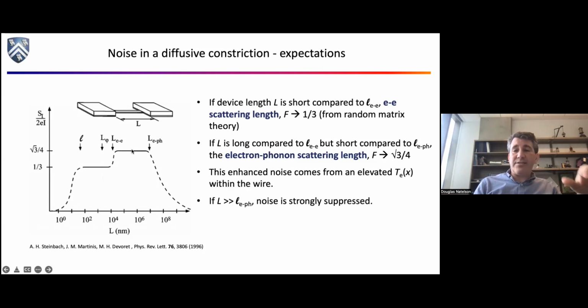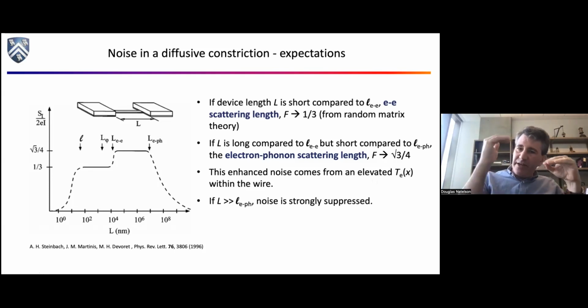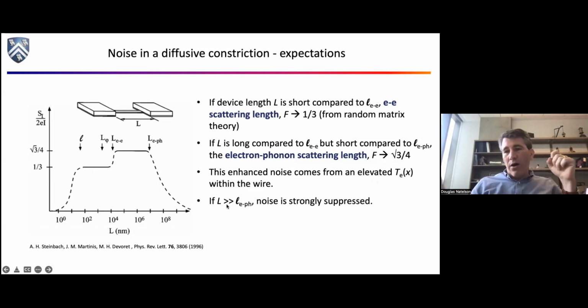Now, if the wire is longer, so the electrons can exchange energy with each other, you can actually work it out that the Fano factor goes up, and it's supposed to be √3/4, which is about 0.433 for those who actually care about the number. And one way to think about that is that there's some effective electron temperature inside the wire where the electrons have shared energy amongst themselves. And that gives you an elevated noise, okay? Now, if the wire is too long, then the electrons can lose their energy to the vibrations of the atoms. And that's called electron-phonon scattering. And so what happens is that if the wire is too long, the noise is completely suppressed.